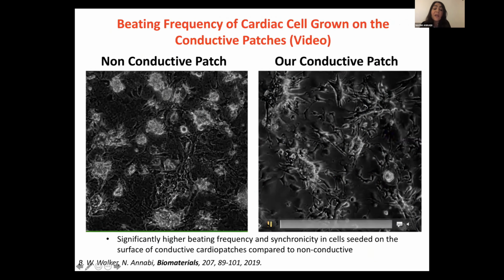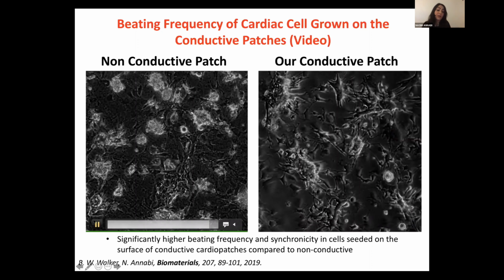And in these videos, I show that on the left side, these are the cardiomyocytes cultured on non-conductive patches. You see that there are beatings in different areas of the scaffold. However, as we make these materials electroconductive, we have synchronized beating characteristics of the cells as we culture them in the biomaterial. So there is a benefit in improving cell function as we work with electroconductive substrate. This is not just from our research team, but there are many other research teams focusing on this aspect, and in agreement with those studies, electroconductive biomaterial can further improve the function of the cells.